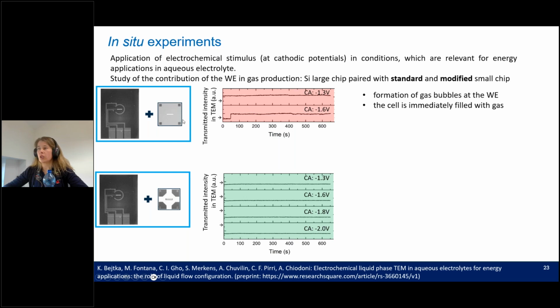So when we perform it in the standard configuration, there is the formation of the gas bubbles at the working electrode, and the cell is immediately filled with the gas. With this, I don't want to say that we don't have any electrolyte anymore on the electrode. We actually possibly have some, because we can run the chronoamperometry, but we don't know if it is covering well the working electrode and the catalyst itself.